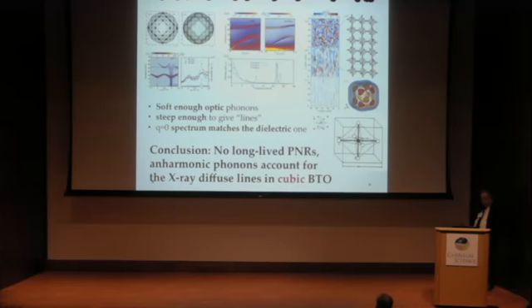Yeah, so our conclusion is that barium titanate in the tetragonal phase has a clear distinction between the time scale of the order-disorder dynamics, which is jumping between the minima, and the fluctuation of the order parameter, the small fluctuations, the ones which are described in terms of phonons. But in the cubic phase, it's not the case. It's very hard, and I would not even know at the moment how to distinguish between them. So there is only one dynamics, at least at 100 Kelvin above TC. I think it remains even down to very near TC. Everything can be described in terms of anharmonic phonons, one soft mode picture at any wave vector. So I would say it's an order-disorder material with a displacive cubic phase.